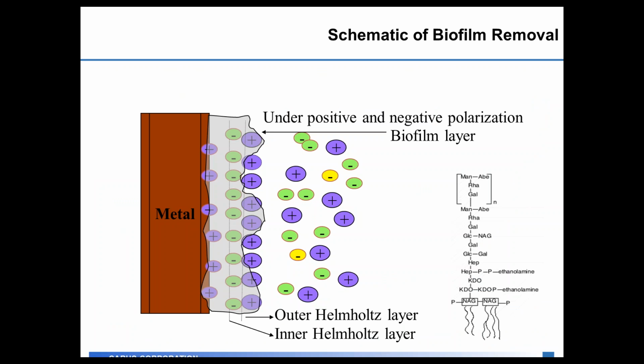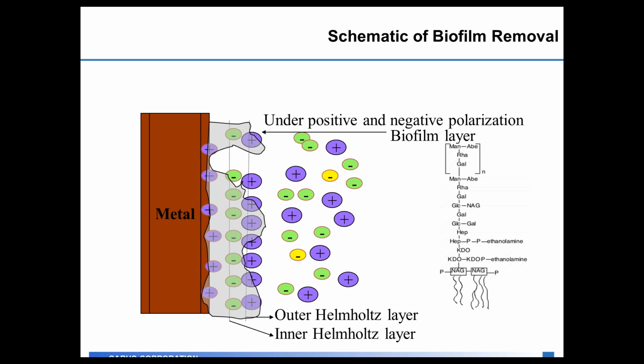One of the things I like to show is a schematic of biofilm removal. It comes up often that when you feed a phosphate product, what influence does it have out there in the distribution system? In this case, you can see the metal pipe surface out in the distribution system, and you can see the biofilm that can grow on the inside of the pipe and the different metals that will be trapped inside the pipe. What will happen is, as the polyphosphate is being fed to the distribution system, it'll actually go out with that biofilm and interact with that scale and actually slowly remove the metals in the biofilm itself.